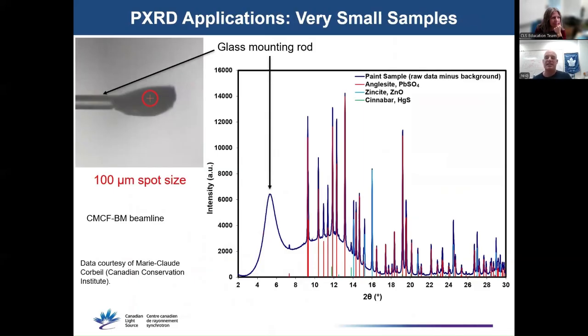The high intensity of the synchrotron allows you to look at very small sample volumes. So many art and cultural heritage samples are really small to minimize alterations to works of art. This is a paint sample from a piece of artwork. It's roughly 200 micrometers or 0.2 millimeters in size. And getting decent data in a reasonable amount of time would be tough for many laboratory diffractometers. The data here was collected in a few minutes using our CMCF-BM beamline.